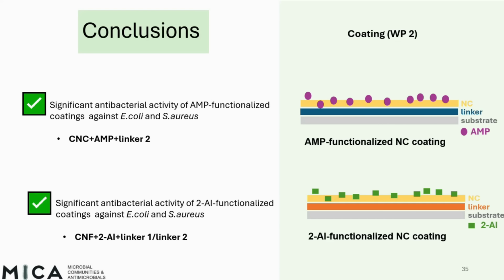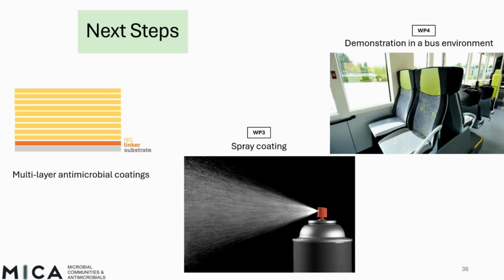So, to sum up, we had significant antibacterial activity of the AMP functionalized coatings against E. coli and Staphylococcus aureus for CNC modified with the AMP just with linker 2. However, we saw this significant activity of the 2AI functionalized coatings with both linkers, linker 1 and linker 2, for CNF modified with the 2AI. So for next steps, we will test the activity of multi-layer nanocellulose coatings with better mechanical properties. Then we will develop a spray coating and we will test it in a real bus environment.